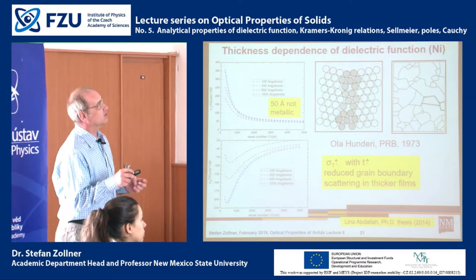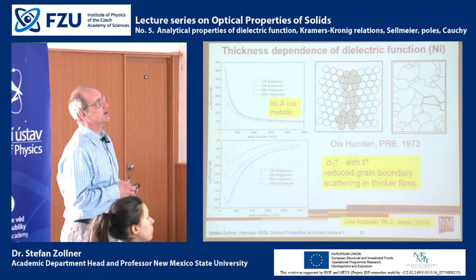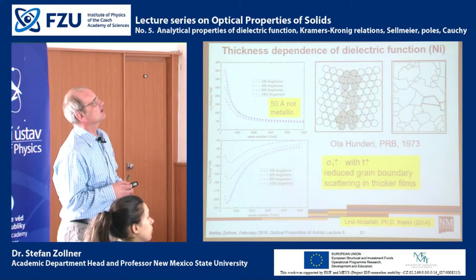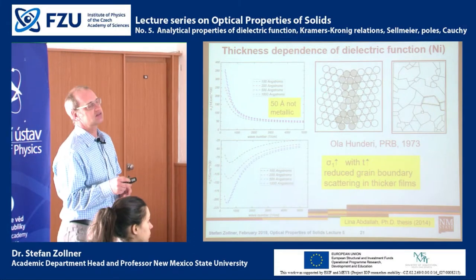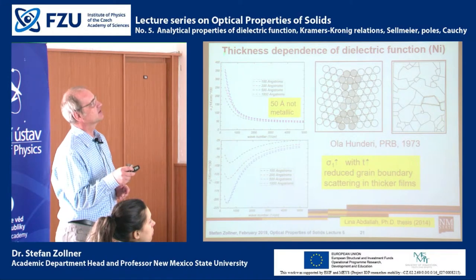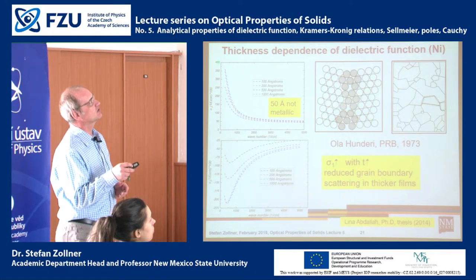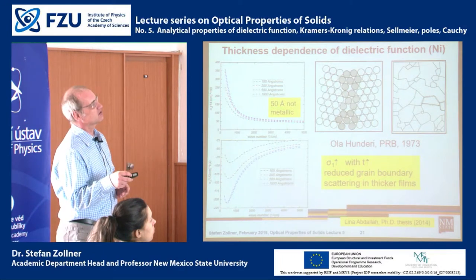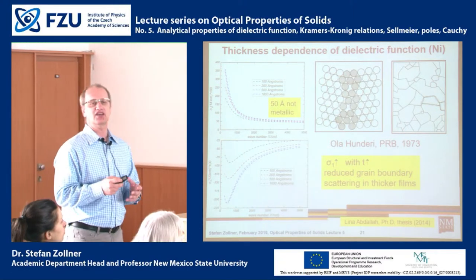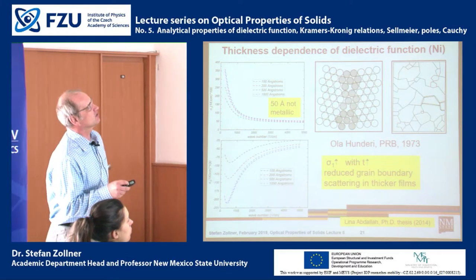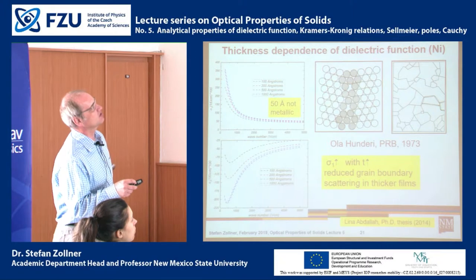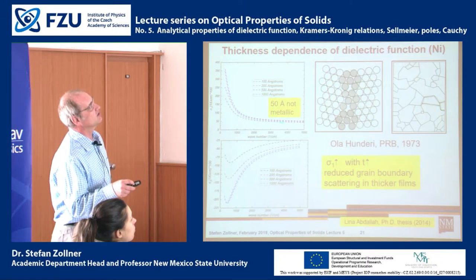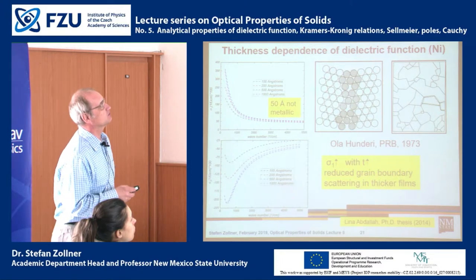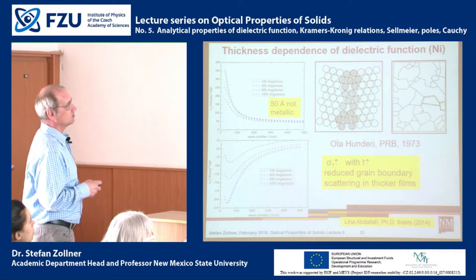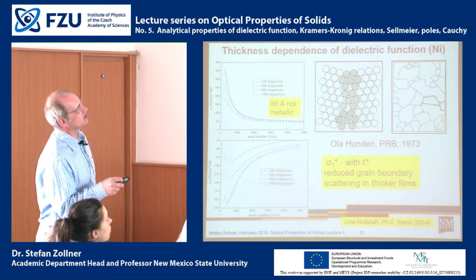And therefore, for our case, we used physical vapor deposition, sputtering of nickel. The 50 angstrom film was not metallic. So here, these films are all metallic. They show that the conductivity increases at the longer wavelengths. So a 50 angstrom film, the conductivity would look like an insulator. There's a band gap somewhere because the islands have not merged. But for the films between 100 angstroms and 1,000 angstroms, the conductivity looks like a metal, that it becomes larger towards longer wavelengths. But you see clearly that there are differences.